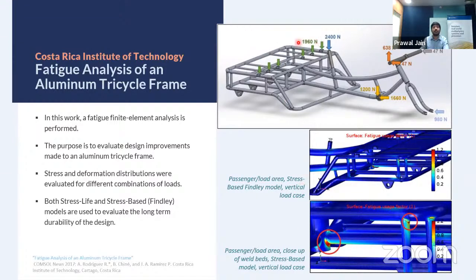In this case, if we see, this was the loading pattern over the whole frame. And we can see that there were some high stress concentrations near the weld beads. And these both plots depict the fatigue usage factor. We can see that wherever we had a quite high stress concentration, the fatigue usage factor is going above one, which means that these are the parts most likely to fail in the given loading conditions.